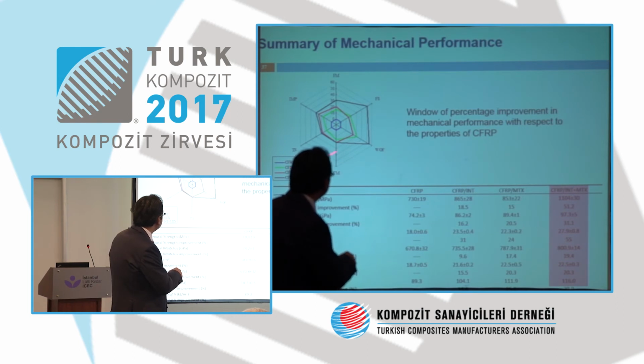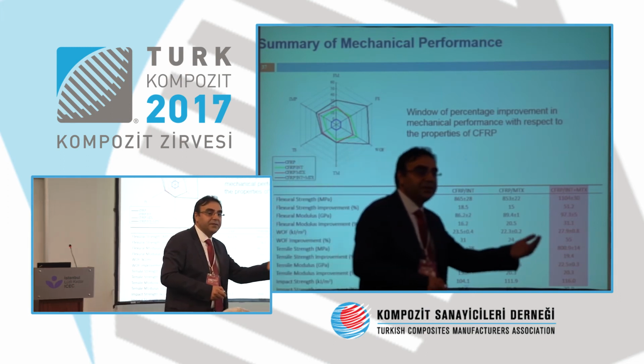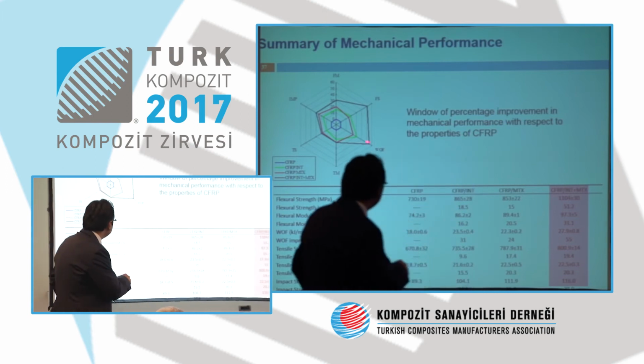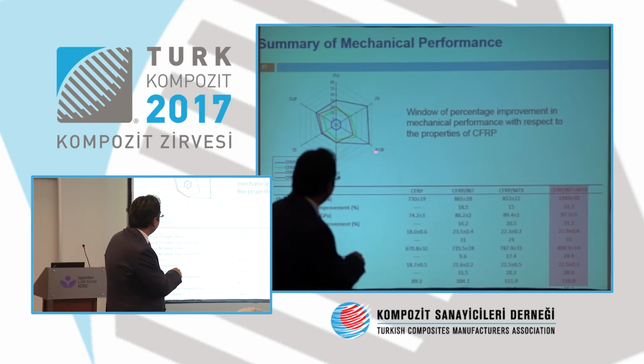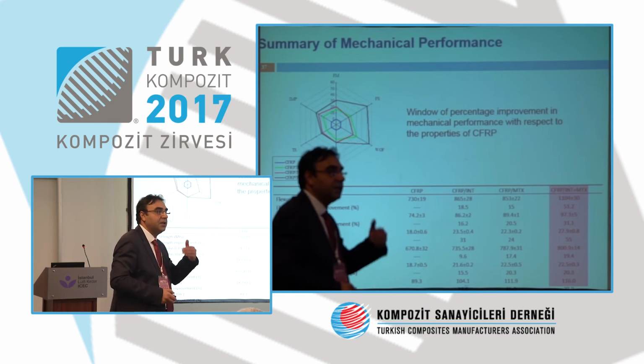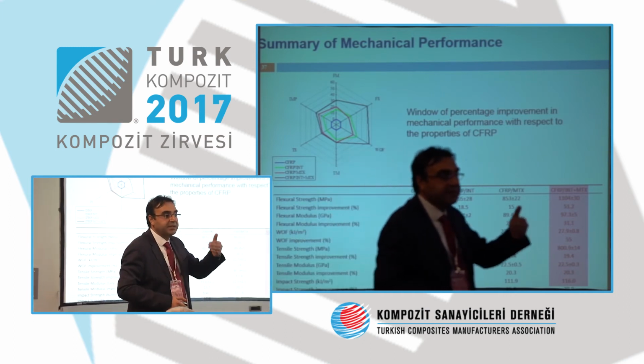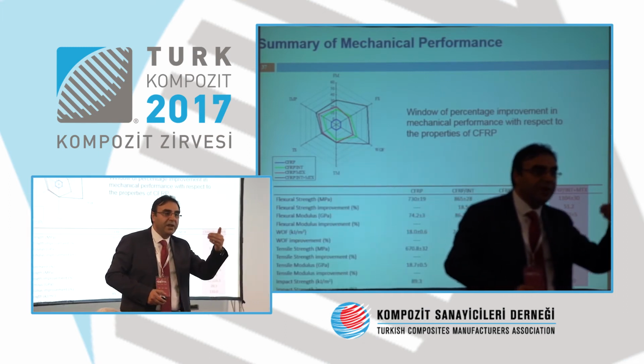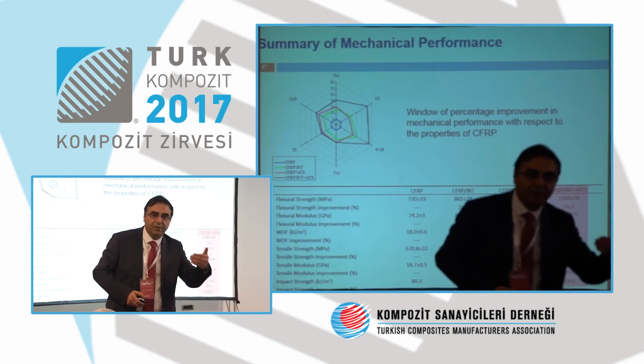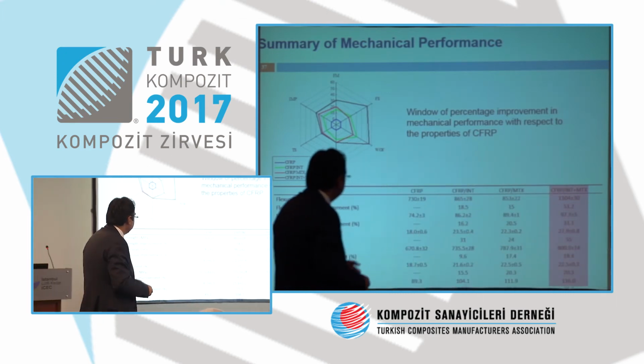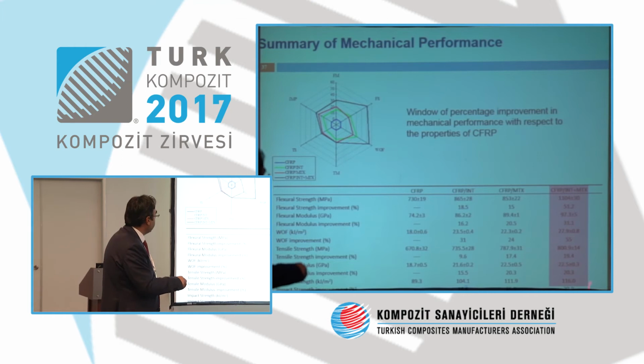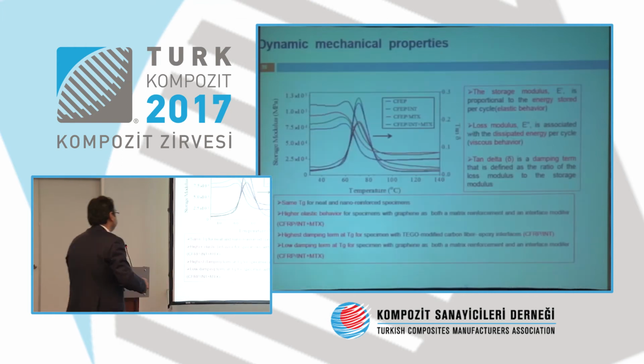The green one is only the interface. The red one is the matrix, but if you reinforce both the interface and the matrix, what you get is really notable: the work of fracture, flexural strength, flexural modulus, impact, tensile strength, and tensile modulus. So you are improving your material significantly without increasing your reinforcement amount of carbon fiber reinforcing materials. And this is the number-wise summary of that one.